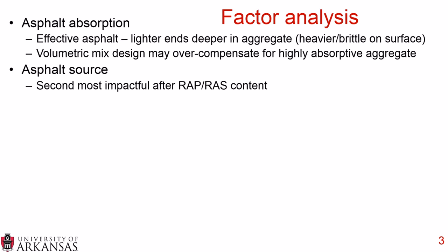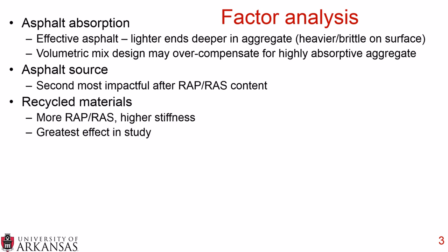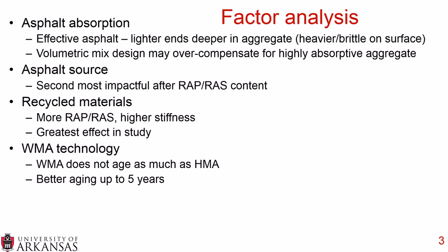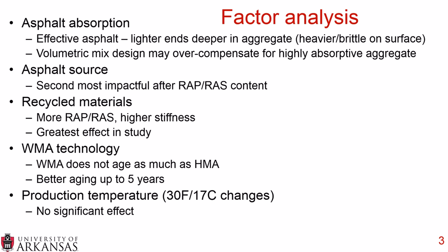They found that the asphalt source was the second most impactful factor after the RAP and the RAS content. They found that more RAP or RAS created a higher stiffness mixture, so more reclaimed asphalt pavement or recycled asphalt shingles created a higher stiffness of the mixtures, and this was the greatest effect in the study. They found that warm mix asphalt technology in general does not age as much as hot mix asphalt, or HMA, and has better aging behavior up to 5 years. And finally, they found that changing the production temperature by as much as 30 degrees Fahrenheit had no significant effect.